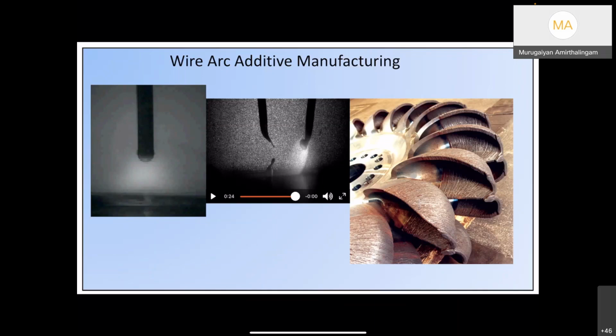I see one example component printed over here. It's a propeller with a radius of about 0.5 meter. So this technique can be used to fabricate large volume components as compared to any other additive manufacturing methods. And the other advantage over here is that any alloy that is weldable can be used to produce components. The knowledge we have in controlling the microstructure, controlling defects, and achieving good mechanical properties is already available in welding. So we can gain the knowledge of welding physics and translate it here to develop a fully fledged near net shape or even net shape component used for in-service application.